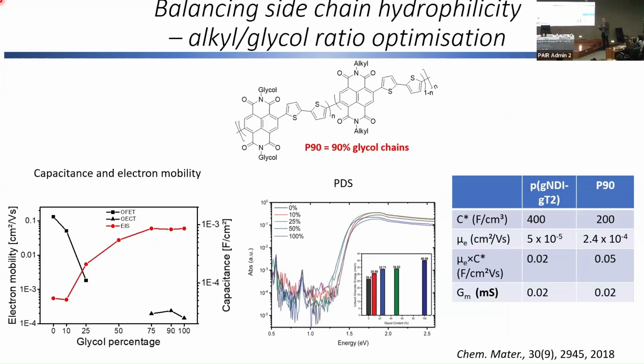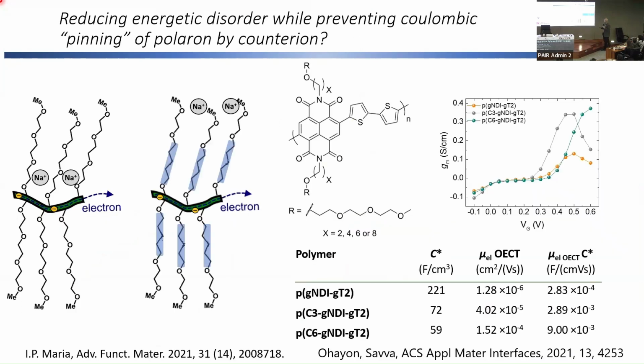Ways to balance this hydrophilicity also are by reintroducing alkyl side chains into polymers. When you do that, you can have some alkyl-alkyl interactions, and this small amount of stitches along the backbone almost act like physical crosslinks, and that helps reduce the swelling on water uptake. So that's also advantageous. I think I'll probably just stop here. I've got a couple more slides to show.